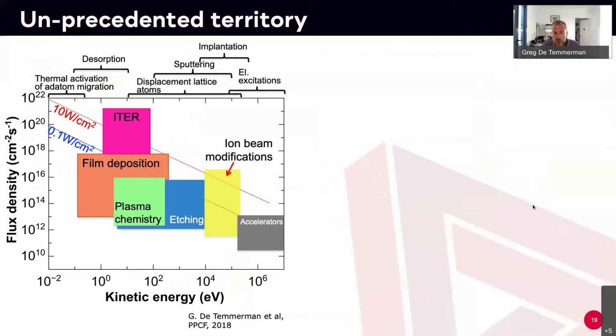Another thing is that you have high fluxes of particles hitting your surfaces all the time, and typically in a tokamak, those fluxes are 1, 2, 3 orders of magnitude higher than any kind of plasma processes we have in the world. So we typically are driving surfaces into a regime which we don't know much about because we have so many particles bombarding the surfaces continuously. And typically you are actually out of equilibrium because you try to put a lot of gas particles inside your surface, and you are exceeding any kind of solubility, or you're actually saturating all of your surfaces.